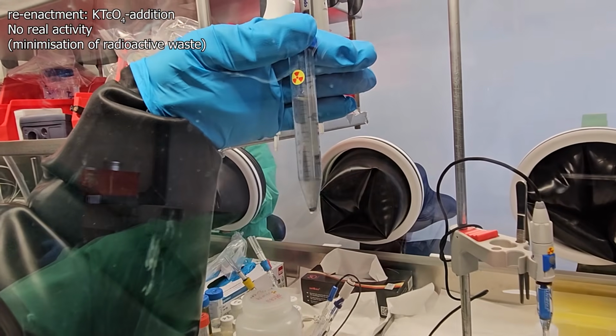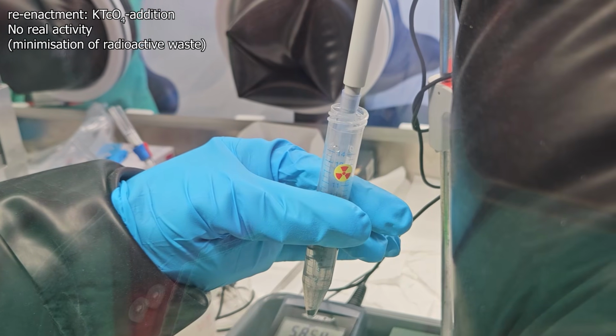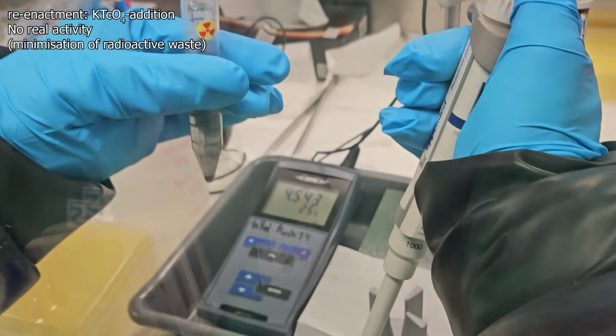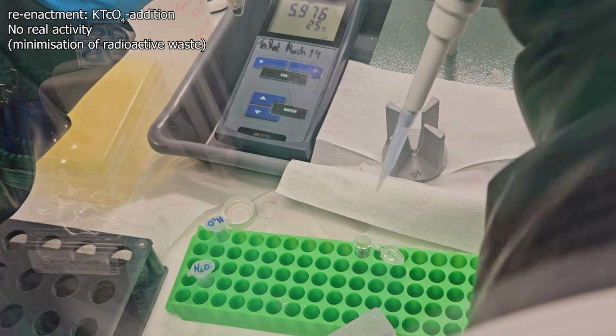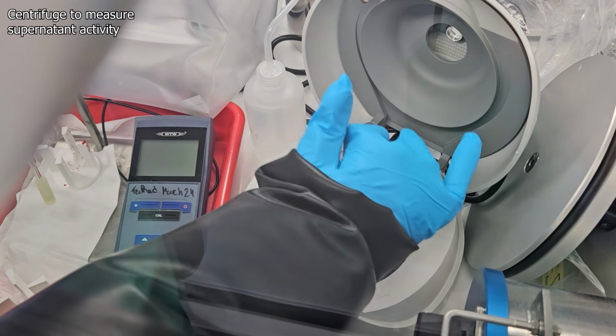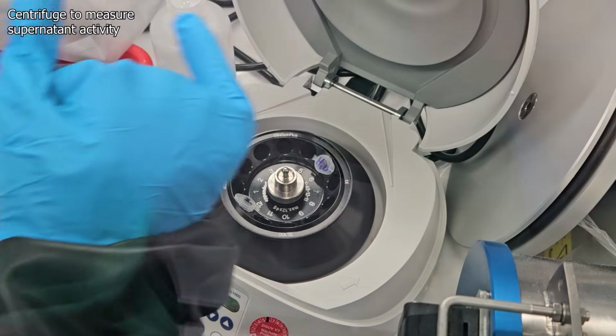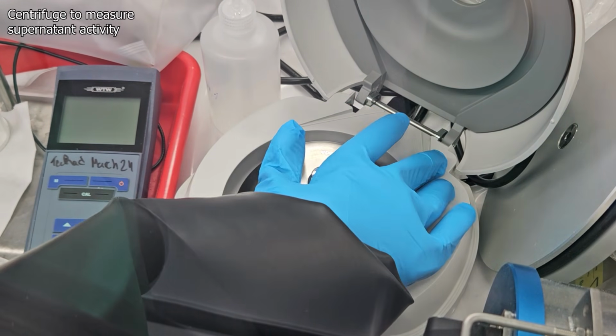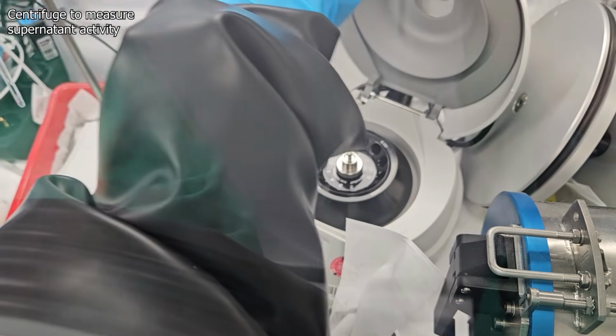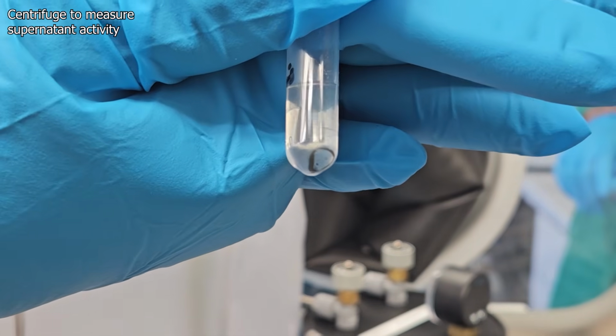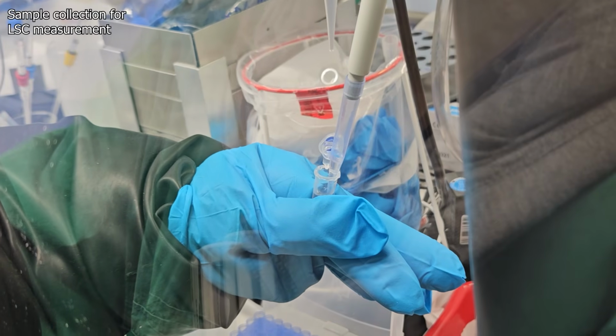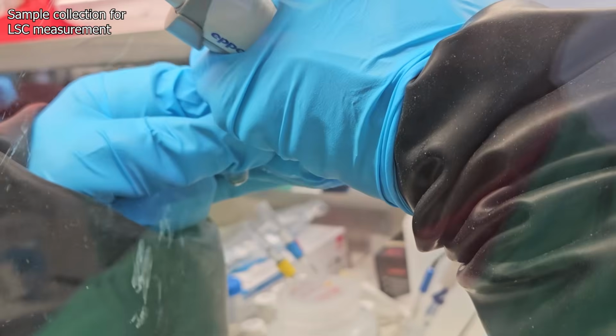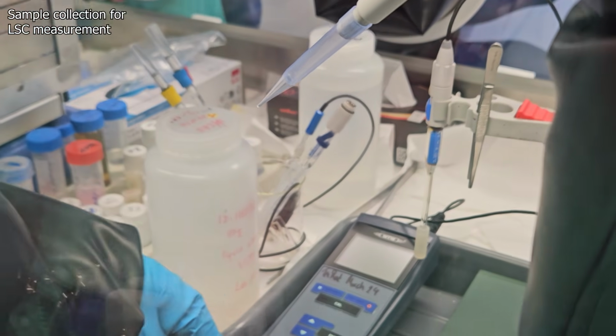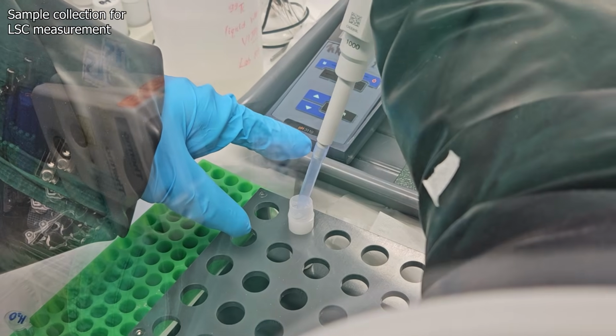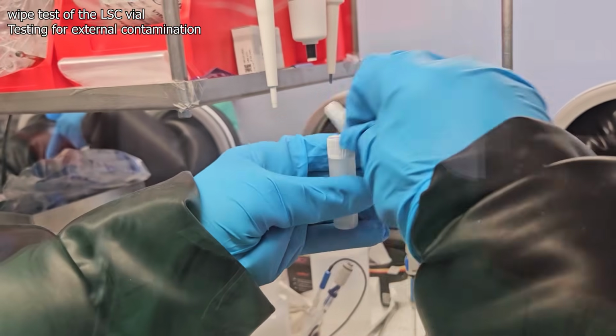In order to determine the remaining technetium concentration after sorption by means of liquid scintillation measurements, based on a known technetium concentration, a sample of the suspension is taken. The suspension can now be separated in a centrifuge tube. We hope that the supernatant is inactive, as this would mean that all of the mineral sediment has sorbed all of the activity. Half a milliliter was taken out of the supernatant and placed inside of an LSC vial.